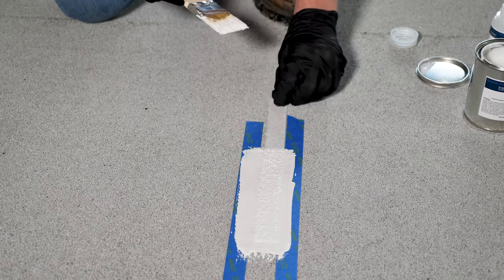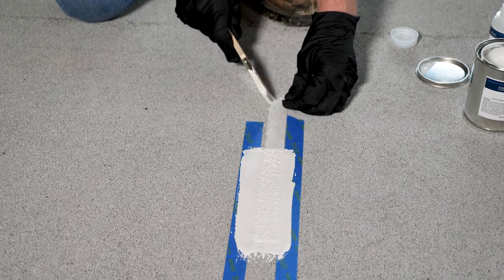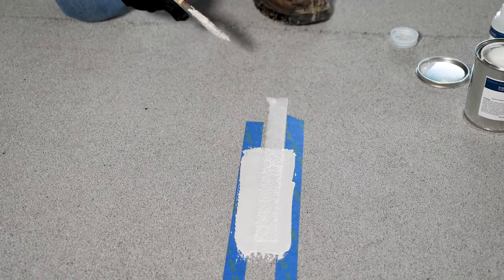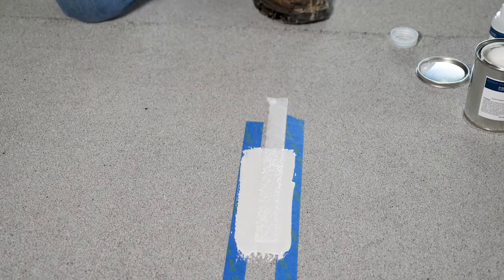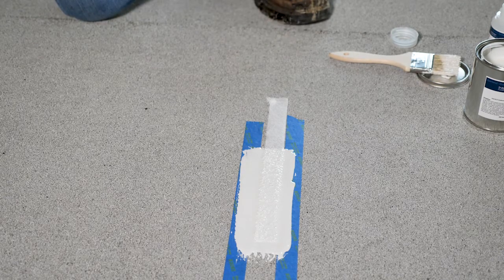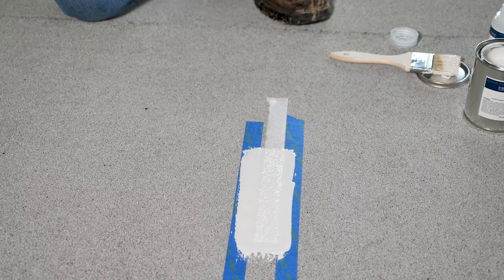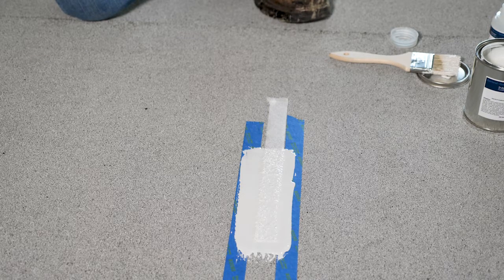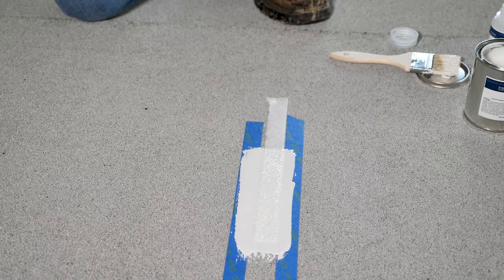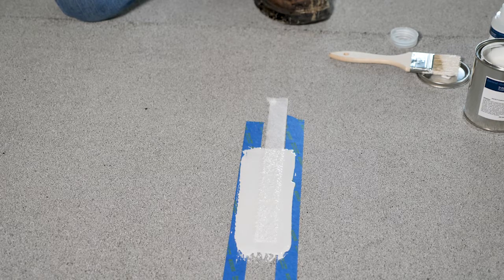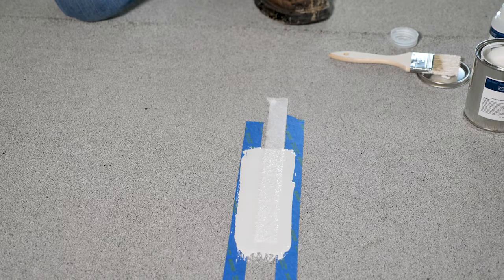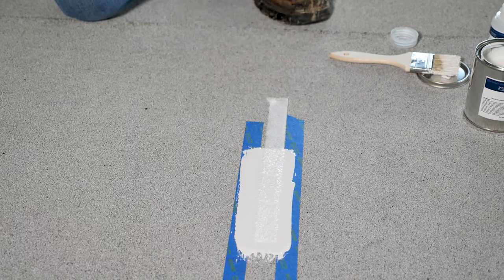Here's a little trick to help discourage wind from taking that flap and putting it back into the coating. You would apply at least two samples on a typical size roof. If it's a very large roof, you may end up with three, four, or five. You might want to put them in different areas—where there's sun versus no sun, or changes in roof direction—to take an average and get a good feel for whether this is going to pass the test.